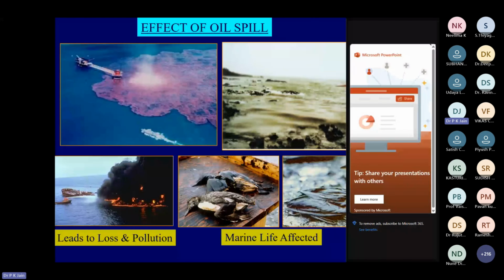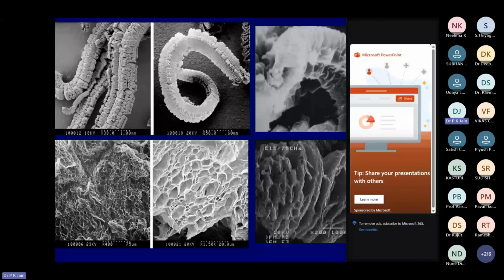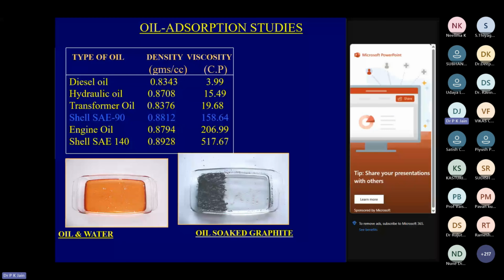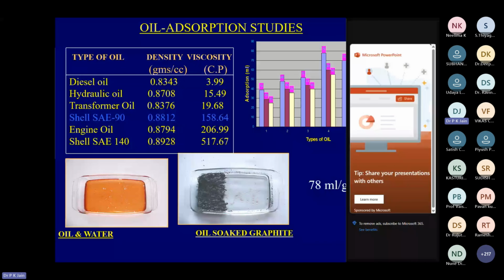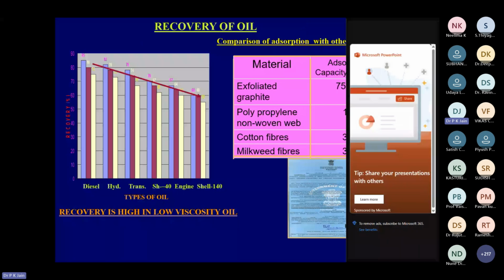Another application is that this carbon is highly porous. It was used for oil spills, to absorb the oil. Whenever oil spills occur and you spread this highly porous carbon, because of the porous structure the oil will go inside through capillary action, and you can recover the oil by centrifuge or by squeezing. It absorbs around 78 to 80 ml per gram, which is very high compared to any other material people have used earlier, like polypropylene non-woven web, cotton fibre, or milkweed fibres. So this exfoliated graphite gives the highest degree of absorption, and we have a patent on that also.